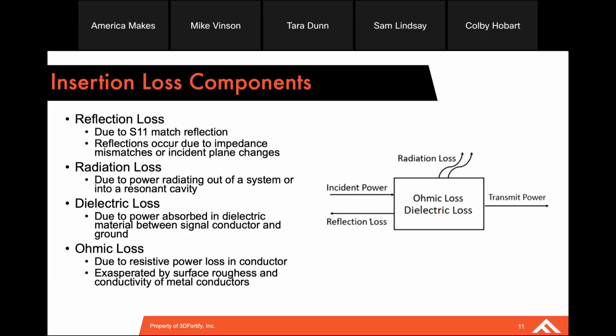as it is applied to the dielectric, and that's very important. If we're going to go after a low loss dielectric and advertise that, we better not be losing a whole bunch of power in our conductor. And you'll see a lot of 3D printable devices with silver ink printed on them in different methods, whether it's inkjet or aerosol jet or dispensed from a syringe. And that silver ink, even when sintered by high temperatures, rarely achieves much over 40% of bulk conductivity of silver. So those lines are very lossy. And the goal here at Fortify is to work with people like Averatek who are putting down high conductivity metals. So they'll get into that later, why their metals are high conductivity and low in loss.